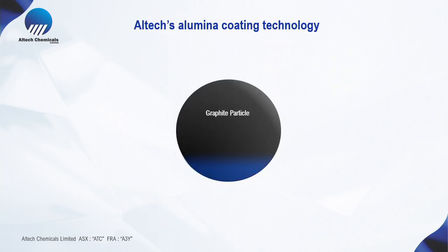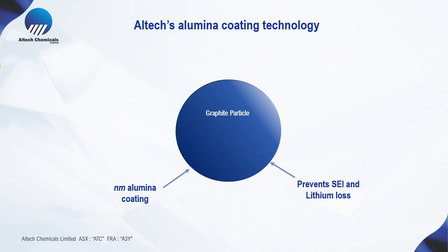Okay, we've come up with a technology using our high-purity alumina to coat these graphite particles. So essentially, we have a very thin layer, and it stops the lithium from forming around the graphite particle, or the SEI layer. Now, the layer of alumina that we form is at the nano size layer, so probably about 2 to 3 nanometers. Now, what's a nanometer?